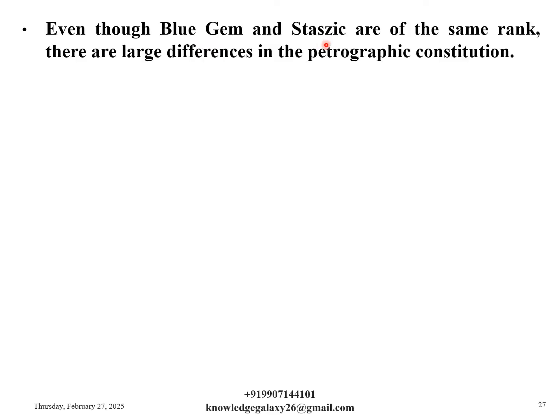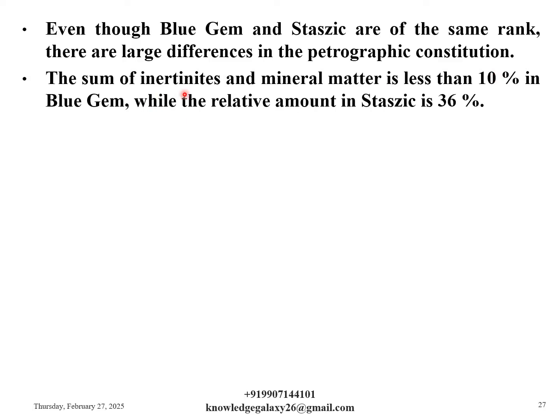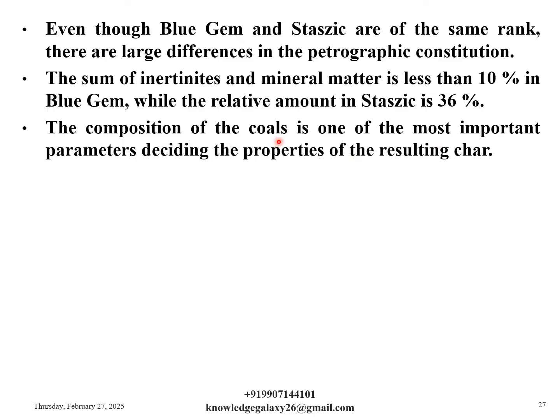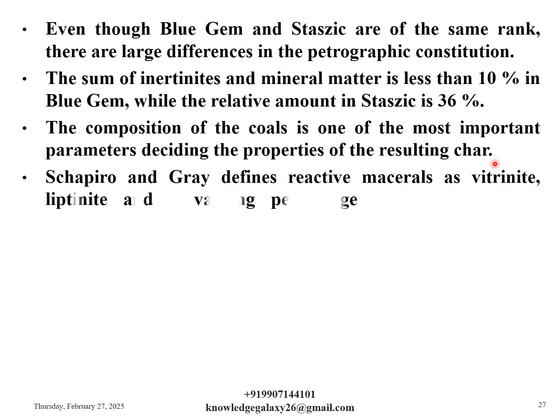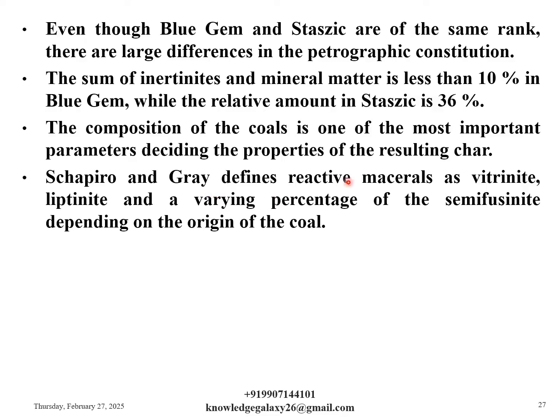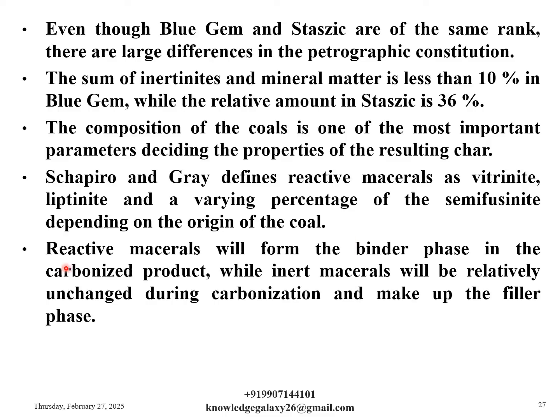Even though Blue Gem and Staszic are of the same rank, there are large differences in the petrographic constitution. The sum of inertinites and mineral matter is less than 10% in Blue Gem, while the relative amount in Staszic is 36%. The composition of the coals is one of the most important parameters deciding the properties of the resulting char. Schapiro and Gray define reactive macerals as vitrinite, liptinite, and a varying percentage of the semi-fusinite depending on the origin of the coal. Reactive macerals will form the binder phase in the carbonized product, while inert macerals will be relatively unchanged during carbonization and make up the filler phase.